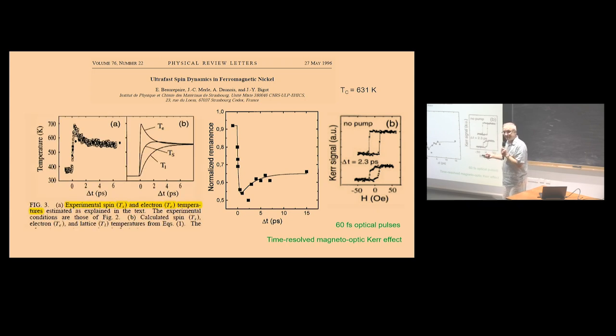They measured the temperature as well. Of course, if you heat up the sample with such a strong optical pulse, you increase the temperature. Because the Curie temperature is 630 Kelvin, you can come to the paramagnetic state, and then the magnetization is reduced. So it's quite a simple effect, or not simple, but quite surprising. This group was able as well to decompose the change of temperature into electron temperature, spin temperature, and lattice temperature. It relaxes, you can see, within a picosecond time scale. So you can really change the magnetic structure with light, but in this case you just change it from the ferromagnetic state to the paramagnetic state. We would like to do something more.